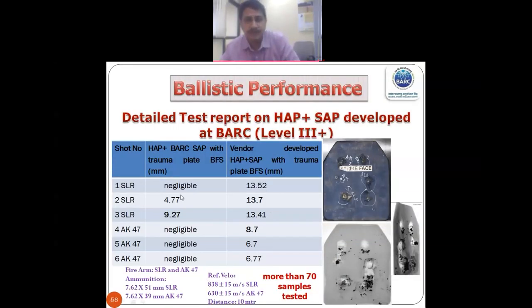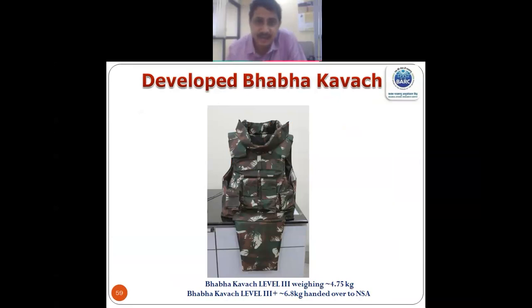I can show you some of the values, that is with SLR, AK-47, what was the backface signature. And here you can see the bullets are entrapped. And if I take the X-ray radiography, even the bullet fragments can be seen. So this is in a nutshell the Bhabha Kavach, and the level 3 Bhabha Kavach weighs 4.75 kg, which is almost 25% to 30% less than the other variety of material available in the market. And level 3 plus is 6.8 kg, whereas what is presently available is more than 10 kg.